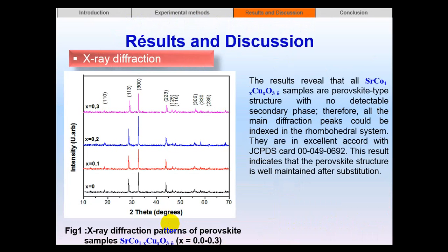Results and discussion. Figure 1 shows the X-ray diffraction of the perovskite samples. The results reveal that all the samples are perovskite type structure with no detectable secondary phase. Therefore, all the main diffraction peaks could be indexed in the rhombohedral system. They are in excellent accord with JCPDS card 00-049-0692. This result indicates that the perovskite structure is well maintained after substitution.